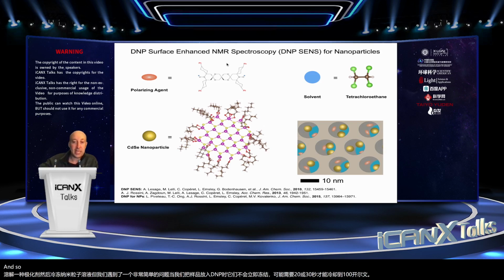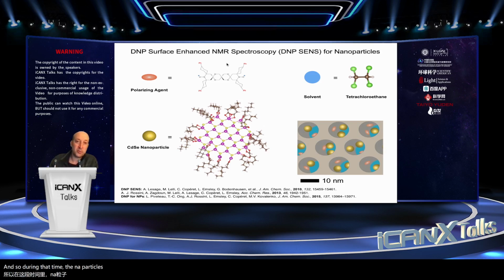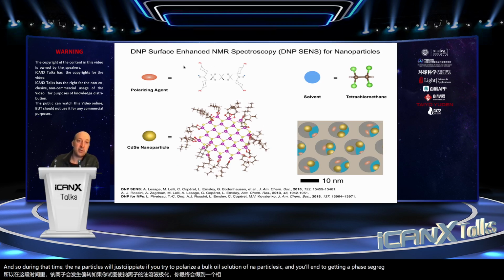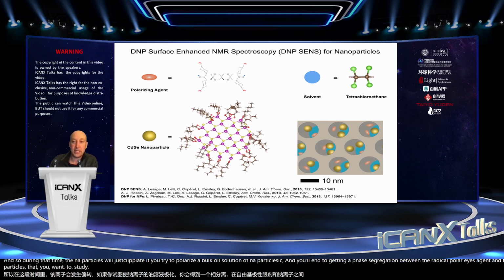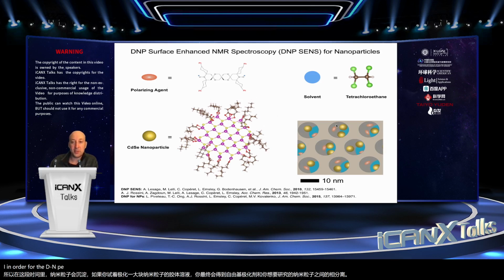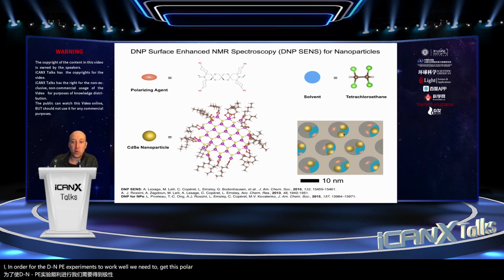And so during that time, the nanoparticles will just precipitate if you try to polarize a bulk colloidal solution of nanoparticles. And you'll end up getting a phase segregation between the radical polarizing agent and the nanoparticles that you want to study. In order for the DNP experiments to work well, we need to get this polarizing agent within a couple nanometers of the target material that we're trying to polarize. So Maxim and Christophe came up with a really simple solution to this problem.